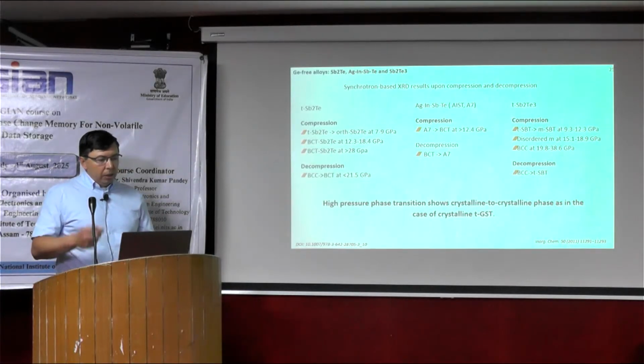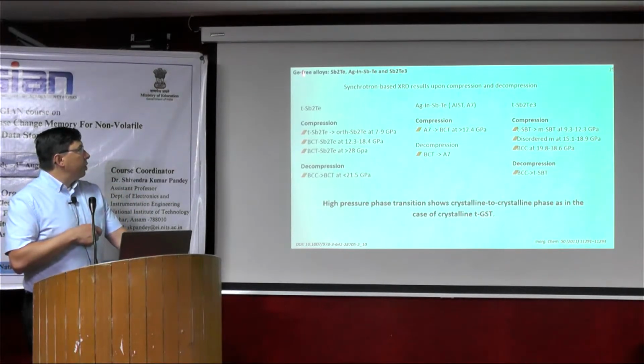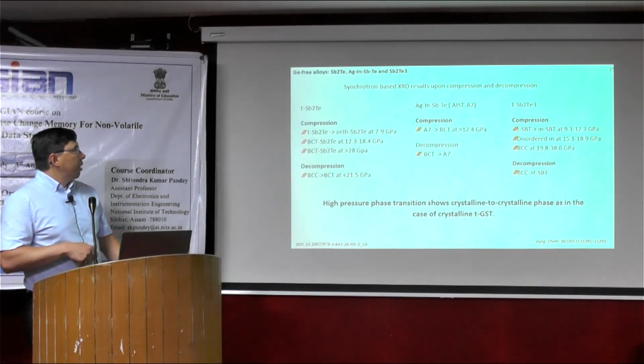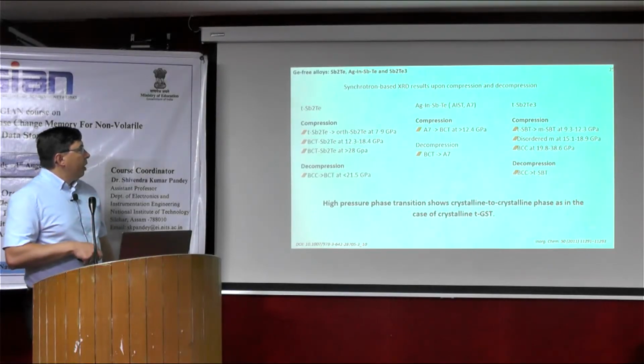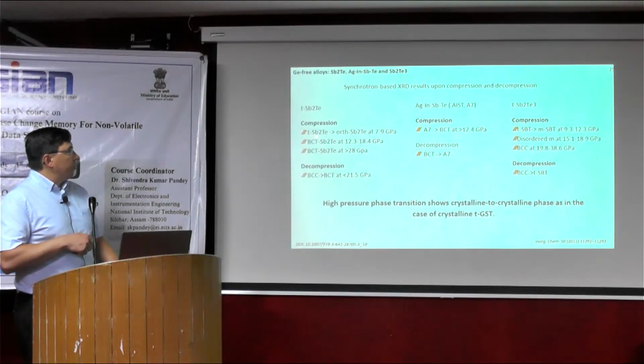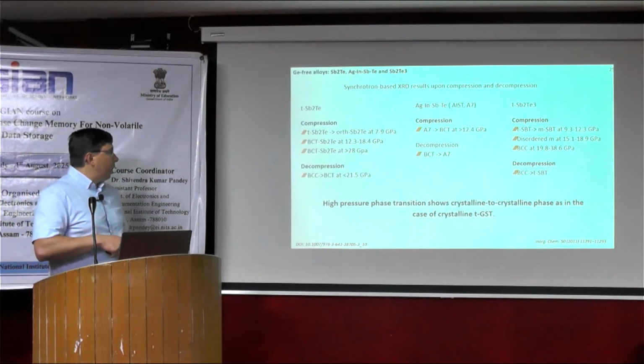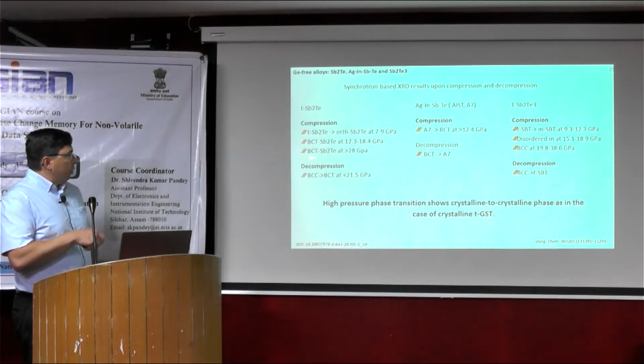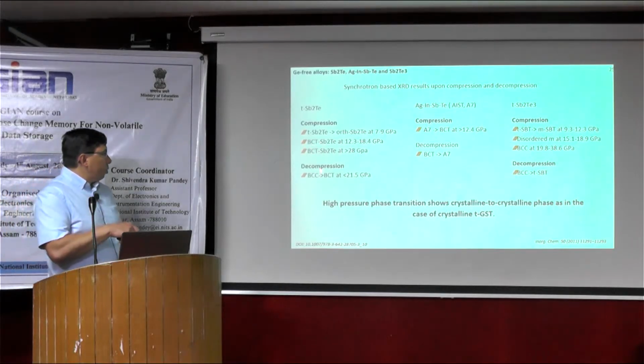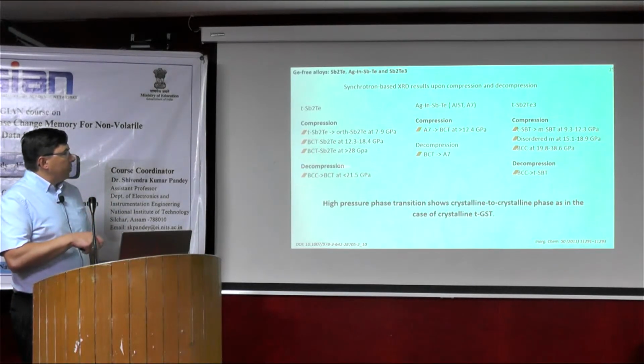Also, some phase changes in other systems, in germanium-free alloys like antimony telluride, AIST, and antimony telluride. In the trigonal Sb2Te3 on compression, this phase is transformed to the orthorhombic phase, then to the BCT, and it stays in this phase until 28 gigapascal, where it transforms to the BCC. Sorry, it's a mistake. It should be BCC. And then the BCC transforms back to the BCT.